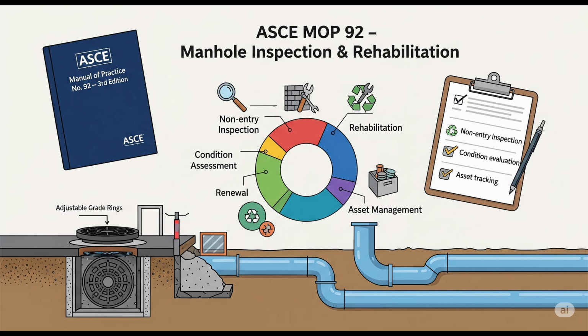So, assuming the prep is perfect, what are the main types of coatings and liners? You mentioned cementitious. Right. Cementitious liners, these are special mortar mixes, much stronger and more chemically resistant than regular concrete. They can stop infiltration, provide full structural rehab, and protect against corrosion, sometimes using special cements or adding a polymer top coat. They can be applied by hand trowel, sprayed on, or spin cast for uniform layering. Spin cast, like pottery? Sort of, yeah. A spinning head throws the cement onto the walls centrifugally, creates a nice even layer.